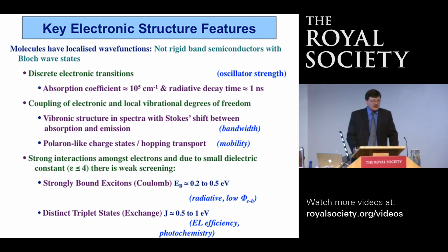They give rise to this large oscillator strength, so strongly absorbing, strongly emitting materials. The coupling to the local vibrations gives us a large bandwidth, which means that they emit over a large wavelength range. The mobility is typically low compared to conventional inorganic semiconductors. The fact that we have these strongly bound states means that they tend to emit light rather than separate into charges. And so that tendency to emit light is very good if we want to make a light source. It's not so good if we want to make a solar cell where we actually want to generate charges in an external circuit. And then in terms of these triplet states, there are other things that go on in terms of photochemistry and so on. And we'll leave that to one side for now.